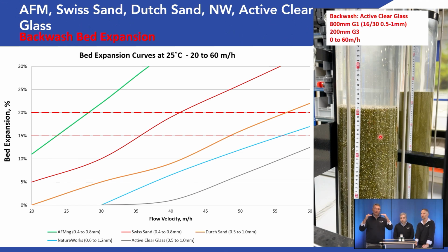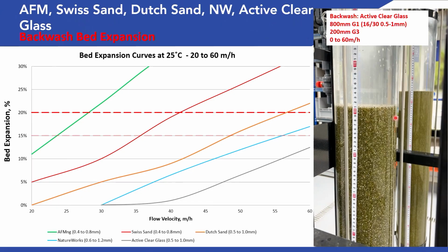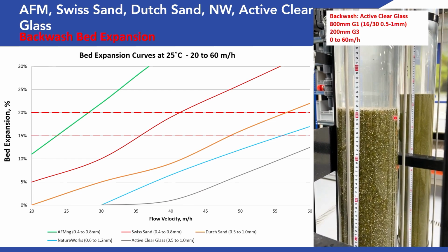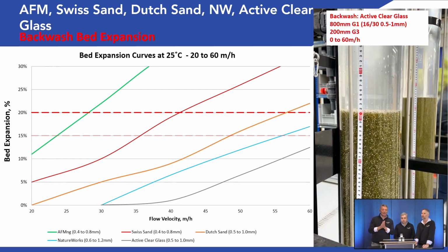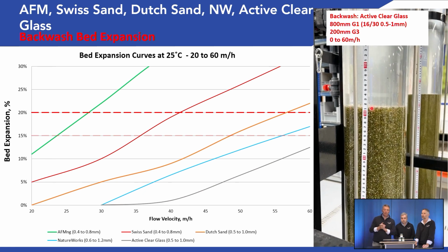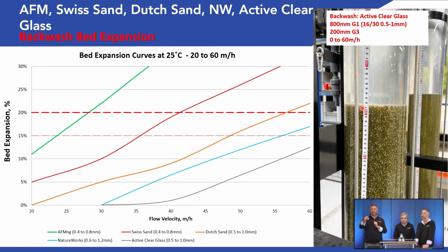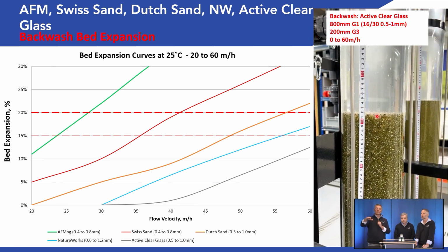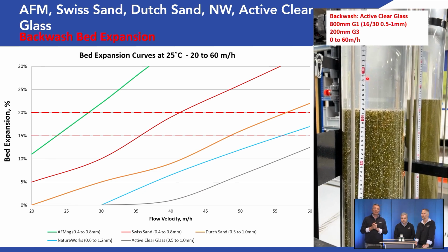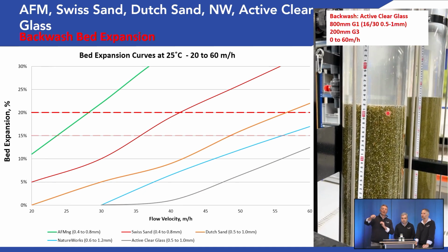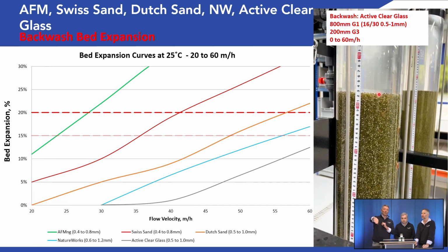Well, here we come to backwash, and filtration is always a 2-step process. One is to collect the particles, that's filtration, and then you have to backwash it. You have to release them completely, and therefore you need bed expansion, and therefore you need fluidization. Maybe Mike, you can run this video here. On the right side you see a video. This is a filter media from Astral called Astral Active Clear Glass, 0.5 to 1 millimeter, and Matthew in his lab is backwashing starting from 30 meters per hour and ramping up to 60 meters per hour. You will see at the end of this video that we have 10% bed expansion, from 1 meter to 1.10.